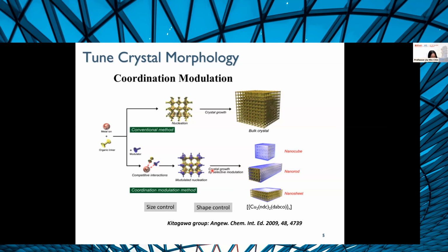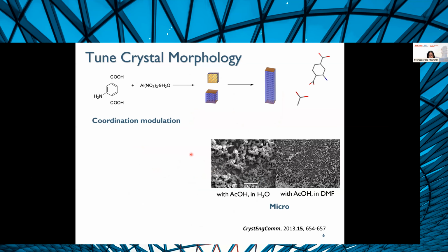So when we first started working on MOFs around 2013, we thought, okay, let's look at a very well-established MOF. In this case, we chose MIL-53 with an amino functionality. And this MOF is characterized by an aminoterephthalic acid linker as well. And it's typically synthesized with an aluminum nitrate salt. And when you synthesize these in this manner, typically you get cuboidal shaped crystals.